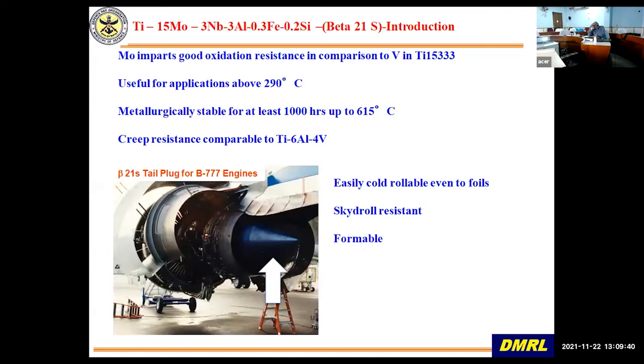And then we are also working on the development of the sheet alloy. This is much better than Ti15333, etc. This has got higher beta 21S, which has got good oxidation resistance and creep resistance. Although beta alloys are not supposed to have good creep resistance, it is comparable to Ti64. As you can see, tail plug, etc. of this material is used.